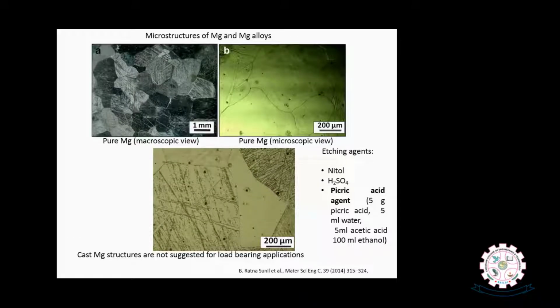For example, here you can see how magnesium microstructure appears. Observing the grains and grain boundaries, details of internal microstructure, is a big challenge in magnesium materials. There are a number of etching agents we can use. Among them, the best etching agent is the picric acid agent, which contains 5 grams of picric acid, 5 ml of water, 5 ml of acetic acid and ethanol, which really reveals the complete details of the grains and grain boundaries. These are typical microstructures of pure magnesium.